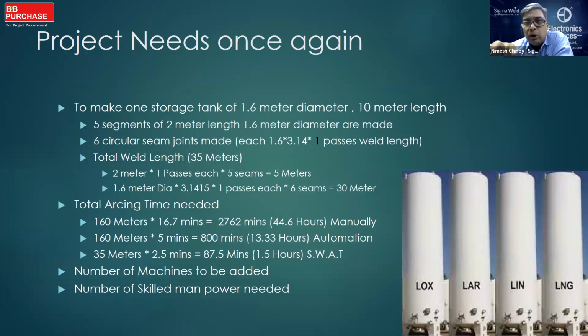Let's conclude and look again at the project needs that we looked at the beginning. If you had to do the same thing using S.W.A.T., the number of passes would be 1 instead of 4. So the weld length reduces from 160 meters to only 35 meters. To top that, your welding speed is now at 2.5 minutes a meter. Therefore, your arcing time required is only 1.5 hours.